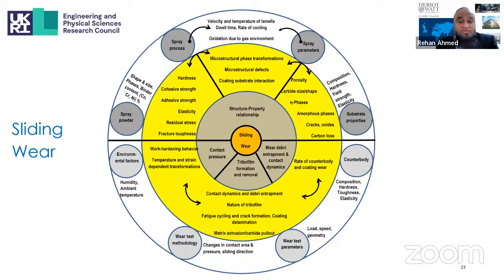And the combination of the two halves of this diagram indicate the complexity and interdependency of the design parameters when we are designing coatings for sliding wear performance. Factors such as the elastic modulus, hardness, and fracture toughness of the coating, and the other materials such as the ball material or the pin material, along with the surface chemistry of the test couples influencing the tribofilm formation, play an important role.